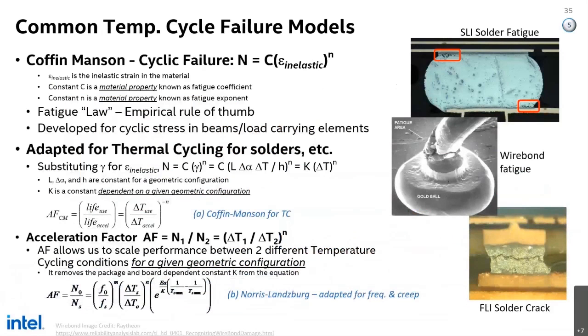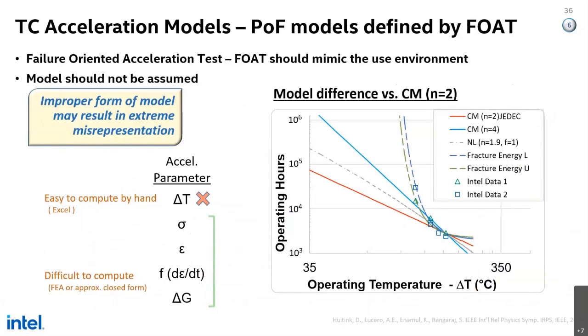The common Coffin-Manson model that's used in temp cycling, all I'm going to say about this slide, and you can look at it afterward, is we've simplified it to call delta T equal to strain. And that's probably not the case. And I have a few examples. One example is this case, where you have a different failure mode that's not related to stress and to the creep and the stress, fatigue, but maybe a more brittle fracture. And so delta T is not the one to look at. You need to use that strain, and you need to probably turn it into a critical crack growth energy.